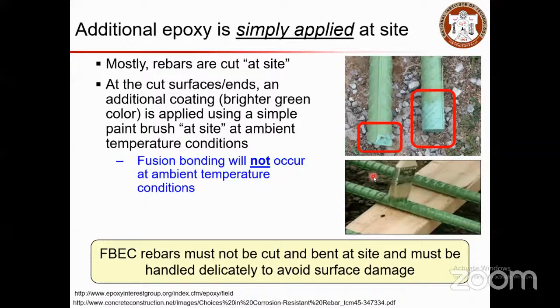So mostly rebars are cut at site. When you do cut at site, there is a possibility, if the coating thickness is more, that it may get peeled off. If it is peeled off, people may not think further, they just tend to fix it then and there and they recoat it. And the recoating is going to affect the performance mostly. So the cut surface is applied using a simple paintbrush.